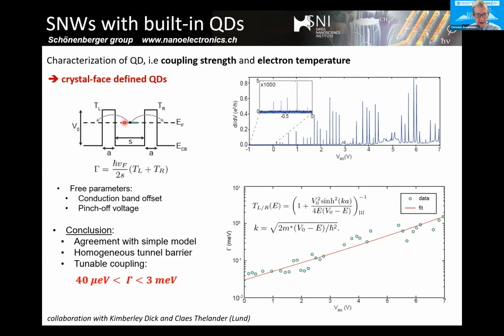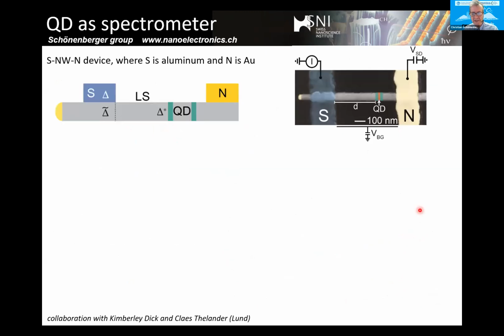The lifetime of the dot states becomes shorter and makes the level broader. So the level broadening, which is measured here, this gamma, will increase with gate voltage. So this is the doping axis, gate voltage. There are more electrons here, and then the barrier gets smaller, and gamma gets larger. And this is a range we can use these systems from about a few tens of micro eV up to a few millielectron volt.